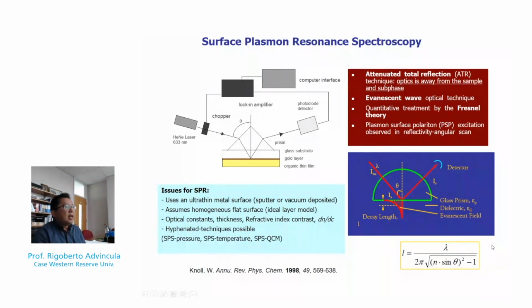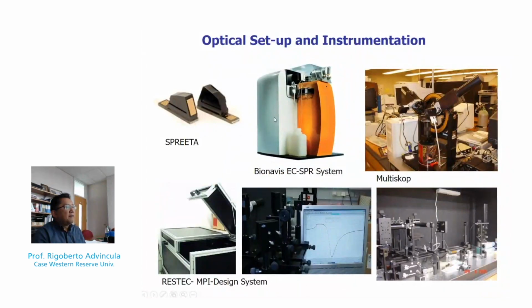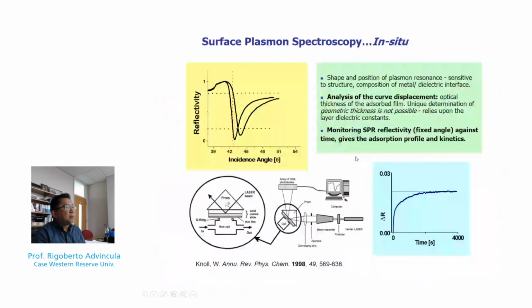Another thing is this open configuration, as shown here, allows us to do hyphenated techniques, which allows us to do a combination of AFM, QCM, put the whole environment so we can control the temperature, do electrochemistry, and even a controlled pressure chamber. Now, as you can see here, various experimental configurations of the SPR. The two on the side are setups that we have in our lab, as well as the middle one. But you can have a commercial setup that is optimized for flow conditions, as well as sensors that have a small footprint. Now, how can we use this otherwise as a sensor?